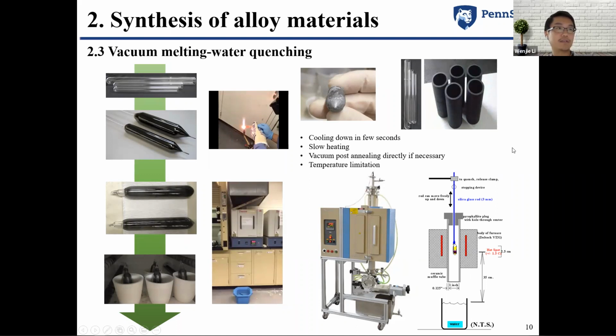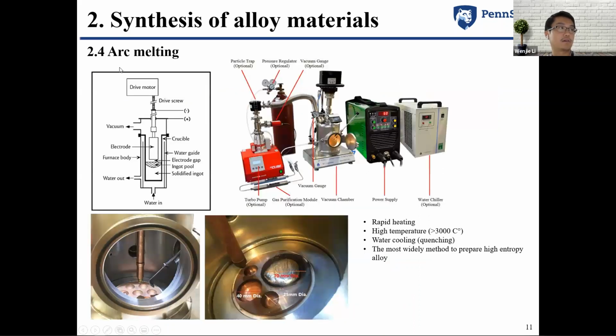The only limitation of this method is that it is limited by the quartz that we use. So the melting temperature is limited to maybe around 1300 degrees C, because for this method we can only heat it up slowly, so we cannot really keep the quartz tube above 1300 degrees C for a very long time. In that case, there's another method called arc melting, to provide a much higher melting temperature together with a quenching process.